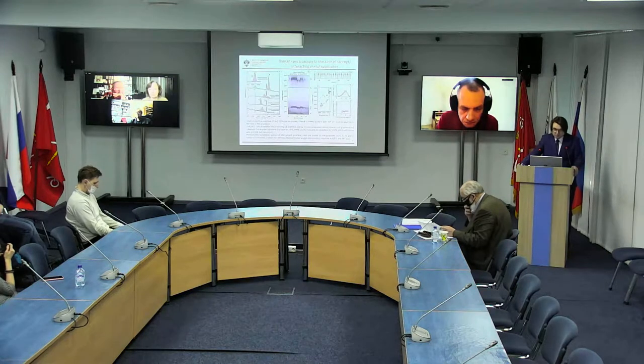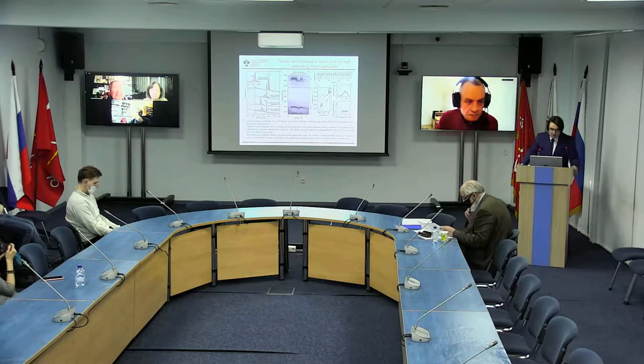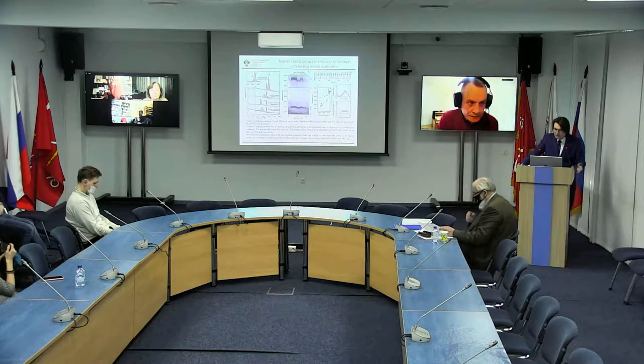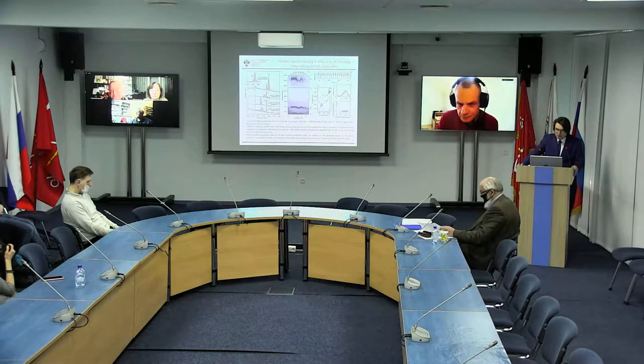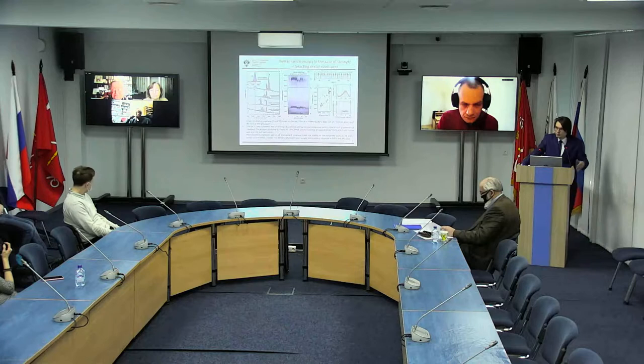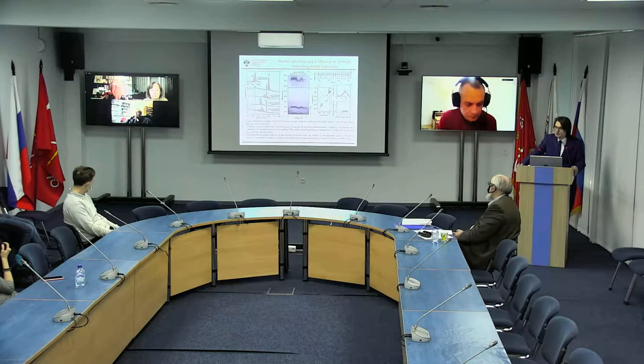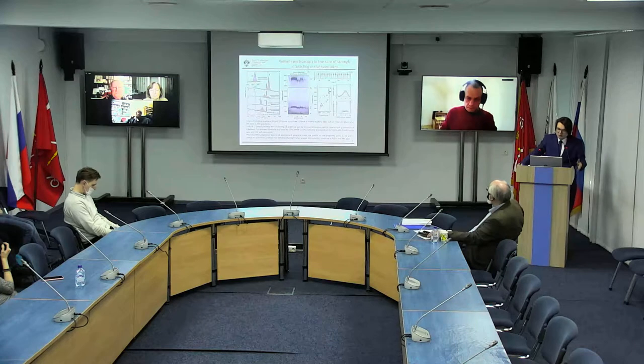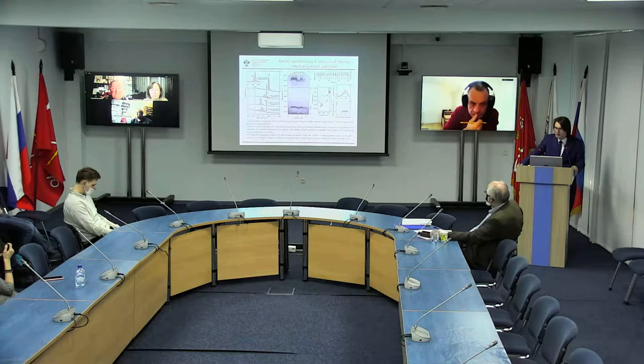Now let's shift to Raman spectroscopy. Overall, single crystalline graphene spectra demonstrated several peculiarities. First of all, there's absence of D and 2D bands in the spectra in any area, and the G band has shifted regarding its position in case of free graphene, and this shift is associated with a strain of graphene due to the lack of correspondence of lattice constants of graphene and cobalt.